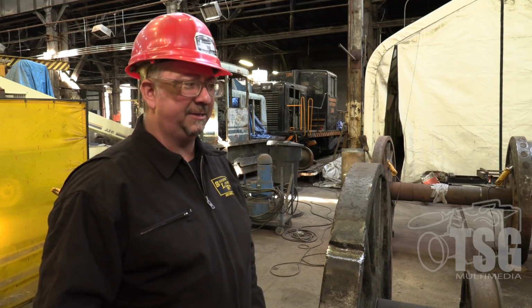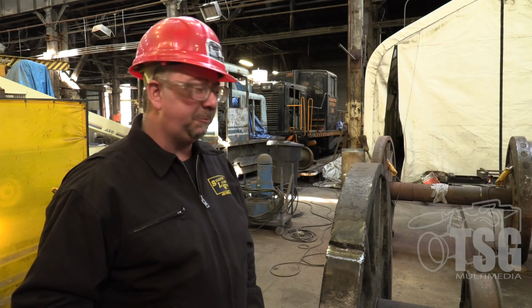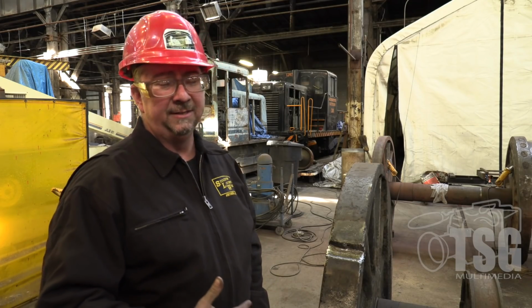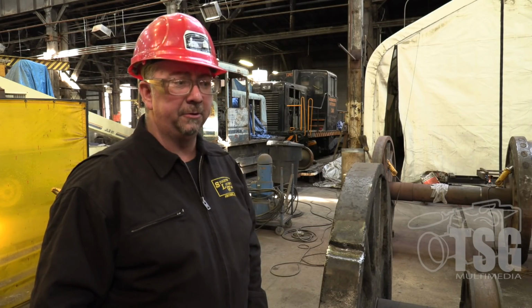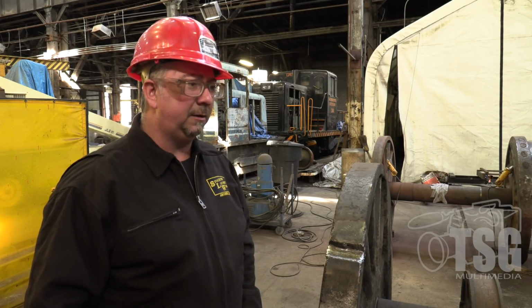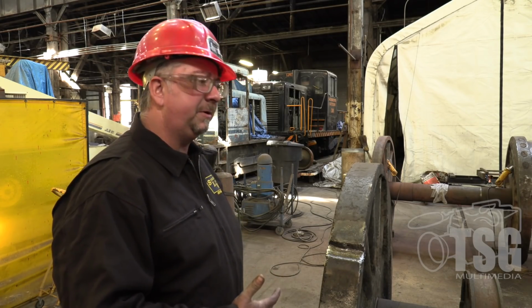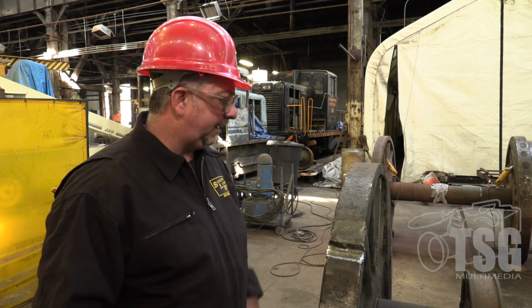the steel casting. Because if you do something along those lines, if you put too much stress into that casting, you can propagate another crack somewhere else, and then you end up just chasing cracks rather than fixing the problem. So there are a number of very specific procedures for modern electric welding, and we are following the pressure vessel standards for what we're doing in terms of the prep, the preheat, the electrode choices, etc., and then using that